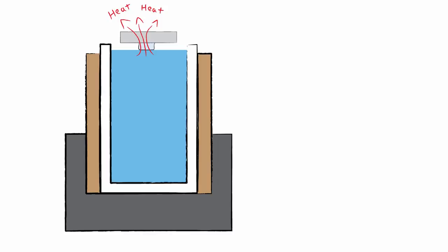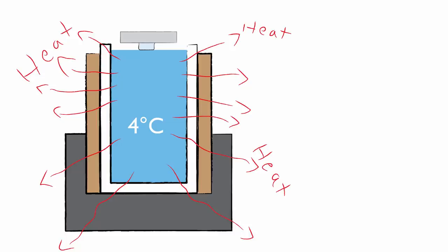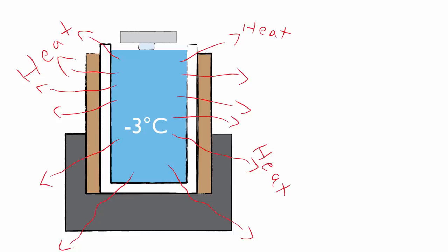Unfortunately, there were dendrites in the container the next morning, so something went wrong. In order to get dendrites, the water must have dropped below zero degrees Celsius at some point — it was supercooled, despite the fact that there was a block of ice touching that water. The only explanation I can think of is that the ice stuck to the aluminum bar was really bad at removing energy from the system. Despite being insulated with foam and a towel, the whole body of water eventually cooled below zero degrees, nucleated new crystals via dendritic growth, and all those crystals later stuck together into a single polycrystalline block of ice.